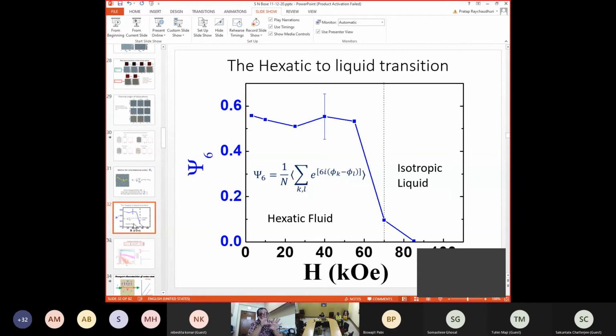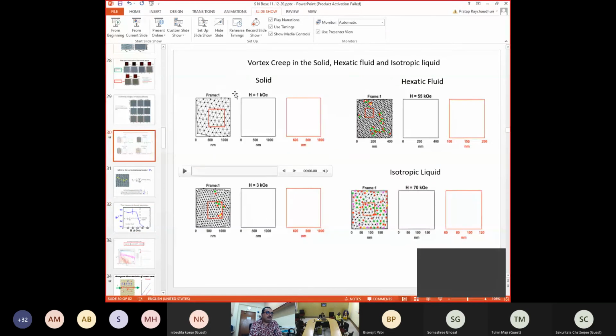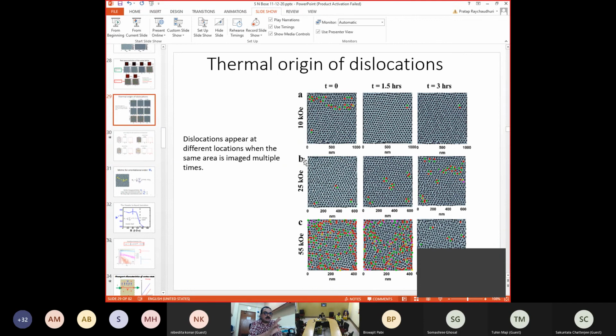So the point is, you can have a solid and a liquid, let's say, coexisting. Now, we have tried to study this from large area images. Large area images are the largest that we can get, which typically are 1.2 micron or so. That has about 1,000 or 1,200 vortices. Within that field of view we don't see such states.